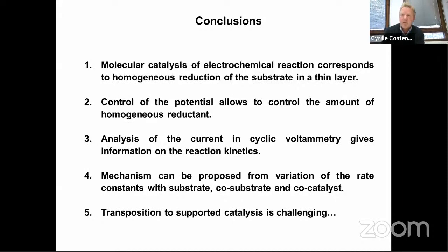Okay. If it's not the case, this means that probably your catalyst is actually adsorbed onto the surface in a way that the active site of the catalyst is kind of mixed with the electronic states of the electrode.